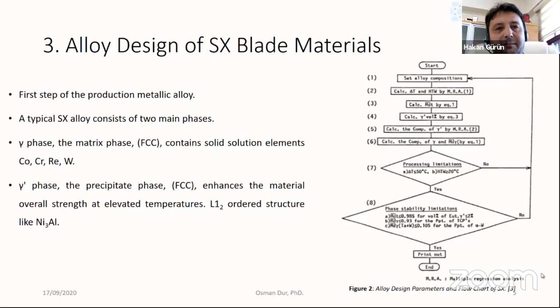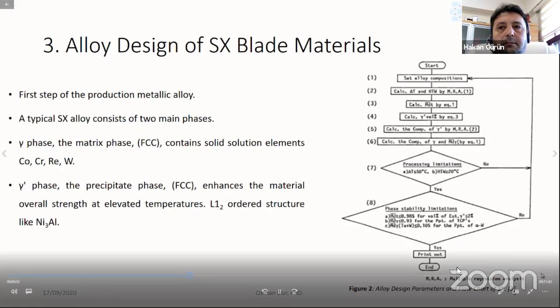This phase can be observed as a face-centered cubic form and enhances the material's overall strength at elevated temperatures, with an L1-2 ordered structure like nickel aluminum. Gamma prime is a quite ductile phase and does impart strength to the matrix without lowering the fracture toughness of the alloy. On the other hand, other phases can be observed, carbides and borides.